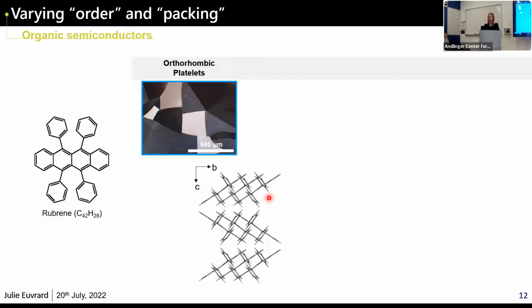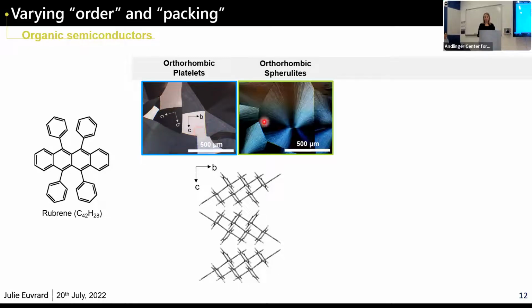And so here we have a very nice polycrystalline film that in this image is a polarized optical microscope image. So each color that you see for each grain is a given crystal orientation. So each grain is highly ordered. Now, what you can also do is induce disorder inside the grain. And you end up with what's called spherulites, where here you no longer have one single color in your grain, but you have a gradient of colors. That means that you have a continuous evolution in the crystal orientation. So you have less order.